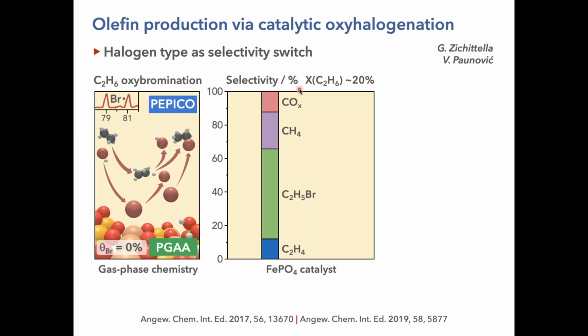But if we go with other alkanes, like for example ethane, to target ethylene, a different situation appears. What you see here is that if you do ethane oxybromination, ethane plus HBr plus oxygen, at a conversion level of ethane of 20%, you get a supermarket of products. You get ethylene, you get ethyl bromide, you get cracking, and you get COx. And the reason is that most of the chemistry is actually happening in the gas phase.